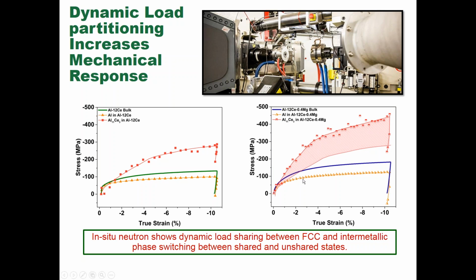And so what happens is that the aluminum phase is a little taller, and that's because of the solid solution strengthening that you get out of that little bit of magnesium that you add. And this phase is much taller. So there's a lot more going on here with the aluminum-cerium phase when you add a little bit of magnesium. Now we don't completely understand that because there's another phase acting there, between either the aluminum-cerium phase and the magnesium, or the cerium and the magnesium, which from a calculation standpoint is there, but we haven't really been able to find it in the structure. That may be because it's nano-sized, or there's some other impact going on that again we just don't understand yet.